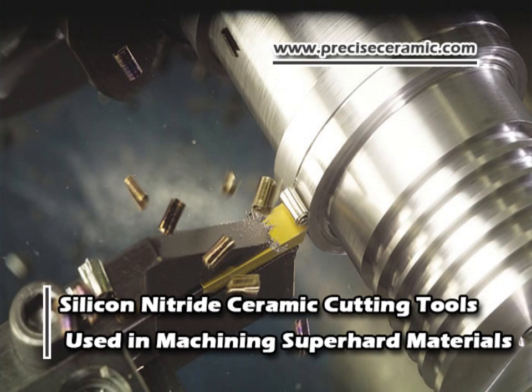Other things that are made with silicon nitride are cutting tools. This is done by pressing it into the desired shape from a powder mixture of silicon nitride and some additives depending on what you are making it for, like adding magnesia to aid in the sintering process and improve mechanical strength. Once this mixture is formed, it is called the green body, and then you can do some initial shaping while the material is still soft. After that, the part is sent to the furnace with a high-pressure nitrogen atmosphere, a process called gas pressure sintering. This high pressure helps to prevent the evaporation of silicon and nitrogen. While at this high temperature, it promotes the densification of the part, where the powder particles fuse together to form a solid, strong ceramic part.